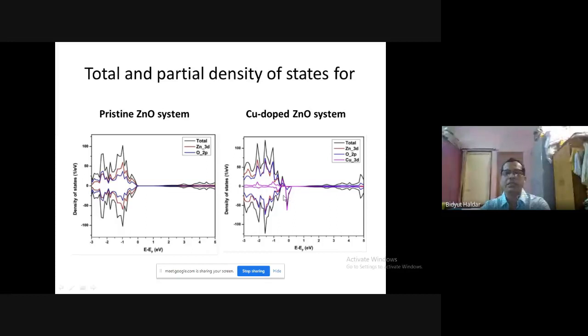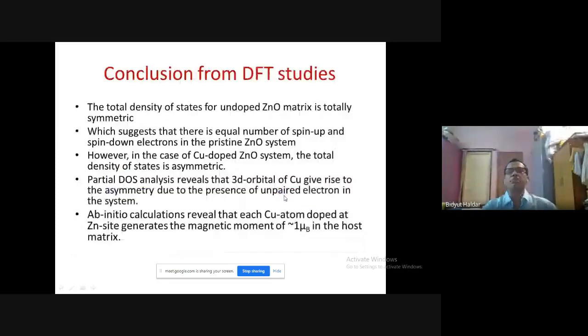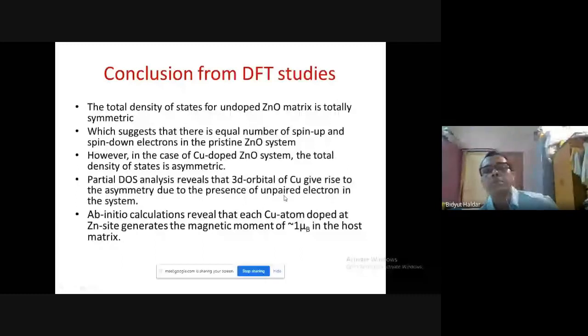Okay, so that is exciting. A brief conclusion that we had from the DFT studies that we already did was that the total density of states for the undoped zinc oxide matrix is totally symmetric, which suggests that there is an equal number of spin up and spin down electrons in the pure zinc oxide system.